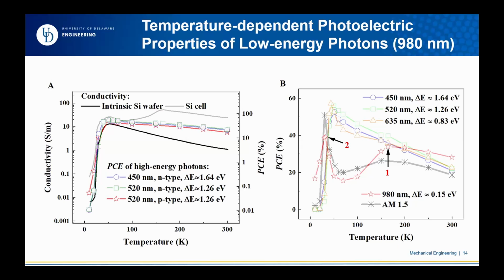After that it decreases, and when people did the experiment, they stopped there because they saw the efficiency decrease. They didn't go further, but there is another peak. For the 980 nanometer laser, it is at about 32 Kelvin. That is similar to the full spectrum, AM 1.5, shown by this curve, which also has a peak at extremely low temperature, about 30 Kelvin. We tested and got this result, and no one reported this before. You can see that even with AM 1.5, you can reach 50% efficiency.